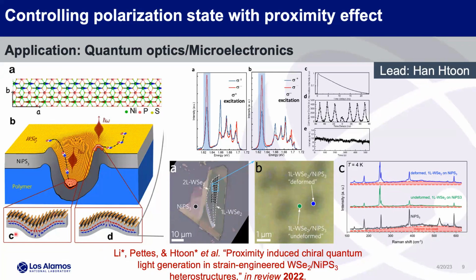But we think for that, NiPS3, the magnet, is an in-plane antiferromagnet. The structure is just in plane. It has different domains. It's hard to see in the way that the theorist plotted it here, but there's one domain that's red arrows on the bottom, and then one domain that's blue arrows on the top going to the right. What we think is we're disturbing the in-plane orientation of that magnet with the punching, because we're punching it with an AFM tip. These are like 1 or 2 microns. You can clearly see them in an optical microscope. But we're disturbing that, and that's creating an out of plane magnetic field that has proximity to the sample that causes that defect.